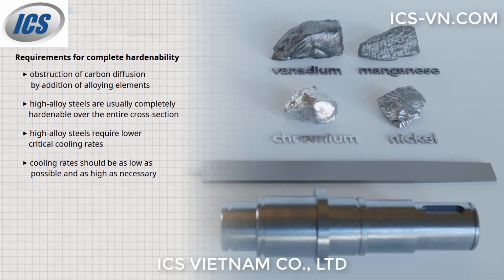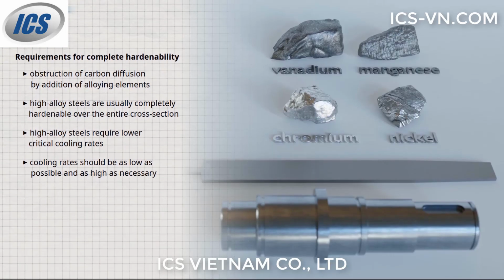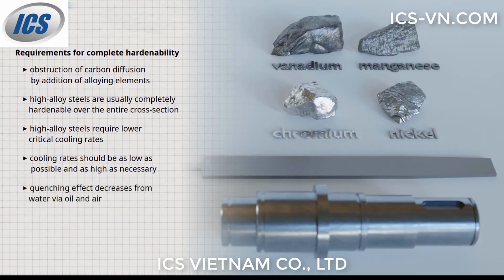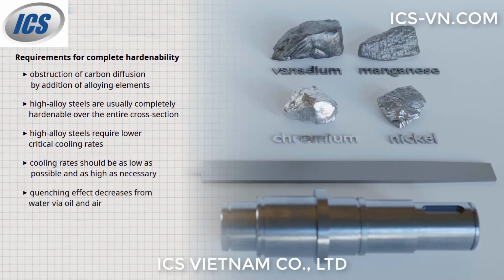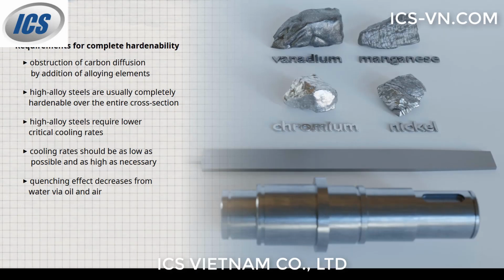The cooling rate can be influenced by the choice of quenching medium. While unalloyed steels generally have to be quenched in water, a milder quenching medium such as oil is sufficient for low alloy steels. In the case of high alloy steels, however, quenching in air can already lead to martensite formation.